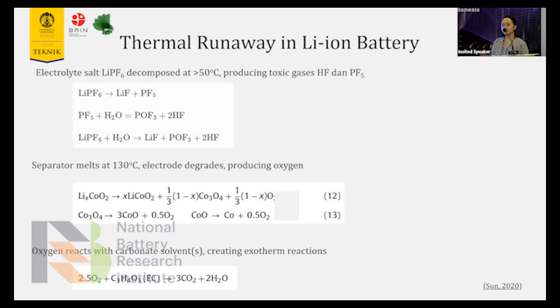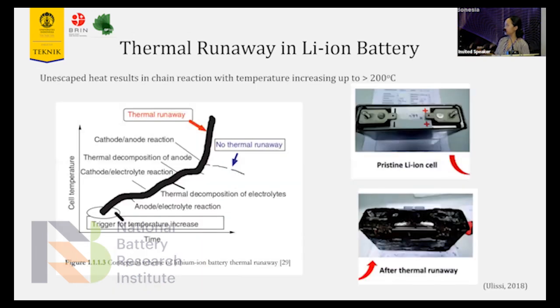So how can leakage and fire turn into a fatal accident? First, the electrolyte salt decomposes at 50 degrees C. So we should remember that high operation temperature of battery can result in a very fatal accident because it produces toxic gases, and the separator melts at 130 degrees C, producing oxygen, which we don't want, because this oxygen, if it reacts with the solvent from the liquid electrolyte, it would create exothermic reactions, and this exothermic reaction, of course, will produce heat, and the unescaped heat would result in chain reactions, and this can result in temperature increasing up to over 200 degrees C.